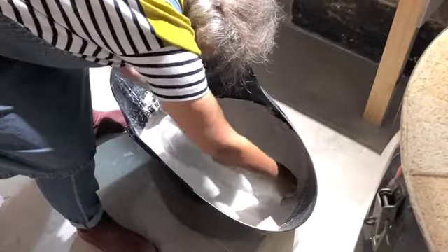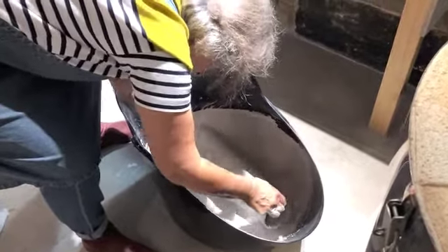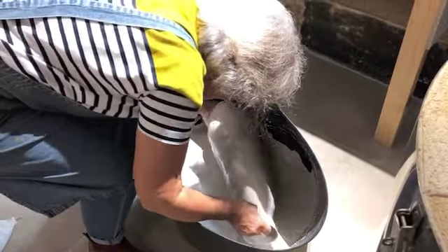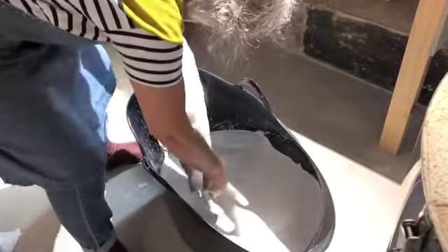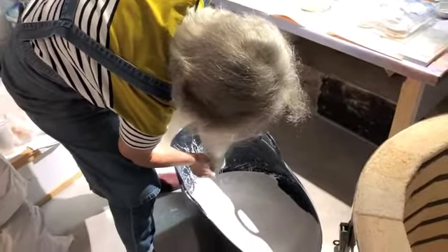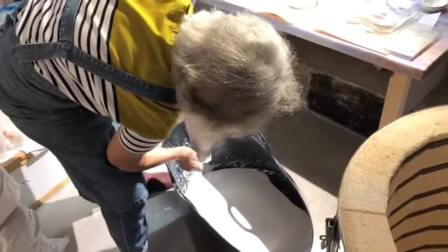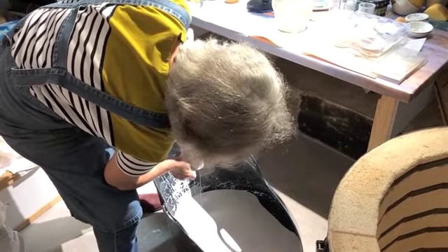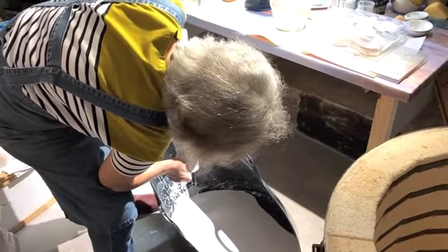Once the clay has completely dried, it is biscuit fired to 1000 degrees Celsius, so it becomes ceramic, but it's still porous. At this point, it is dipped in the glaze. The tin glaze that I use is a prepared glaze from Podmore's, and I have found it to give the best colour response. I have to make sure it is thoroughly sieved and stirred, and also to make sure I have adequate volume to submerge the piece.